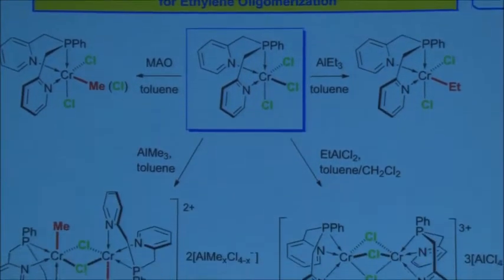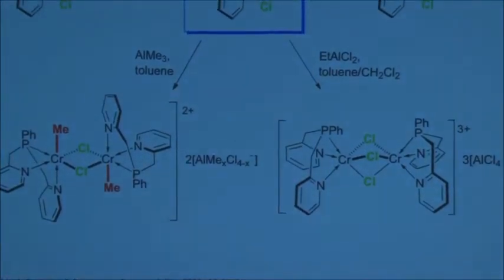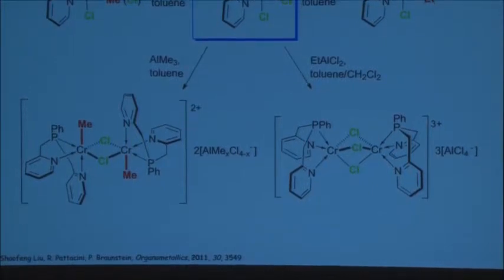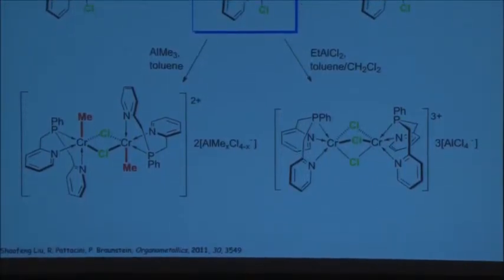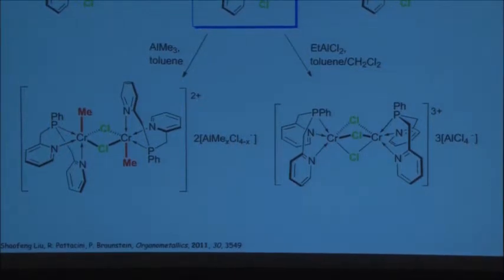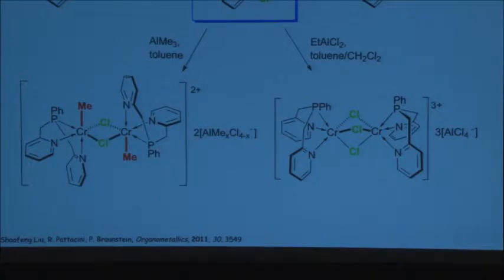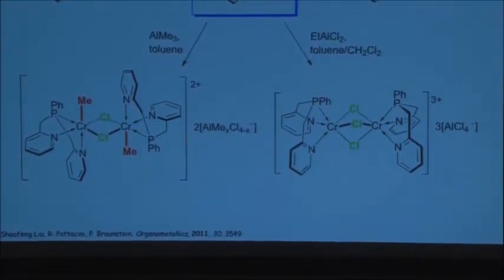Now you take these other 2 catalysts, very popular, trimethyl aluminum, the little brother of the triethyl aluminum, just a shorter chain. It does something totally different. It does alkylate the metal, but also it abstracts some chloride ions. So now we only have 2 chlorides left for the 2 chromium atoms. So the aluminum has picked up some of the chloride and made this a dication. So that's another important function, as I said, of the co-catalyst. It makes the metal center more electrophilic, so more susceptible to react with ethylene.